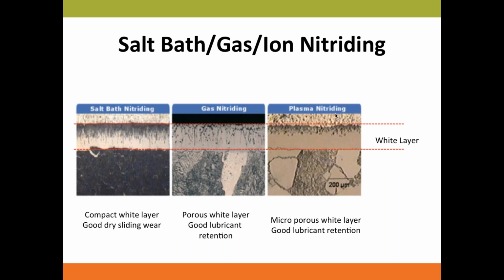But if you look a little deeper at salt bath, gas, and plasma or ion nitride, you can see on these micrographs, on your left, it's a salt bath. I highlighted the white layer, or the compound layer, which gives you the corrosion, erosion, and wear resistance. And the case depth actually gives you the fatigue. You've got to be a little careful about what you're asking the nitride to do. The salt bath creates a very compact white layer, so it's very good for dry sliding wear. And for the gas and the plasma nitride, due to their nature, they involve gas. So if the process is not controlled properly, you can create some pores or porosity in the white layer.